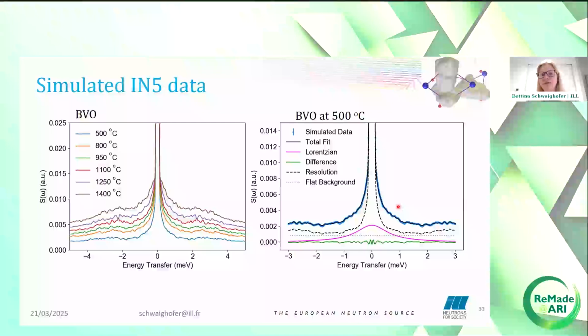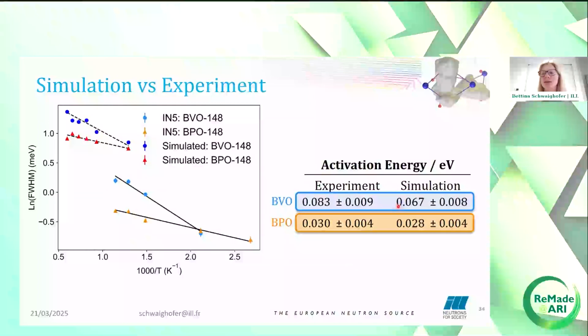Again, the data for BPO looks very similar to this. I'm just showing one example to not repeat myself too much. From the temperature dependence of the full width at half maximum from the simulated data, we could again extract the activation energy. And a very good agreement between experiments on IN5 and simulated activation energies makes us quite confident that what we observe in the simulations is the same process that was observed on IN5.